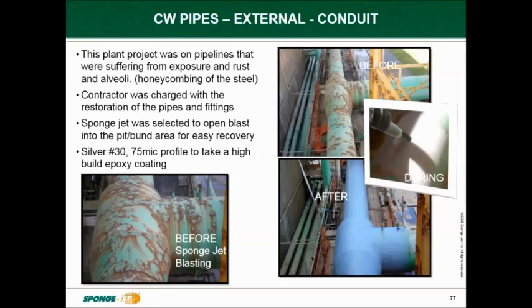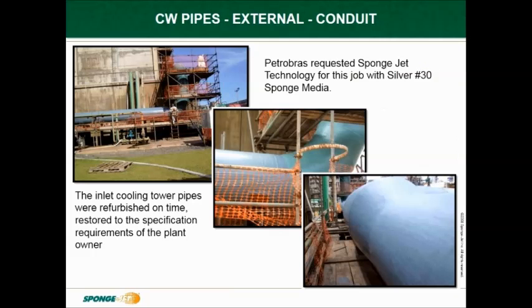The project was performed while the pipeline was in operation. The inset picture is the actual blasting of the pipeline, exposing the aggressive pitting. The sponge media used was silver 30, producing sufficient profile to support the application of a high-build epoxy coating. Pictures of a work in progress, the scaffold around the pipework, all showcasing the finished product.